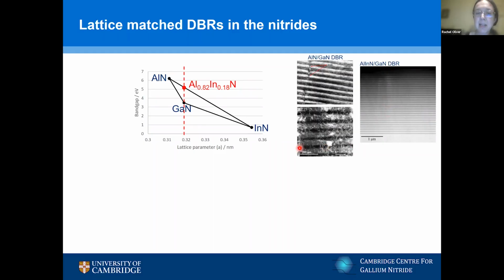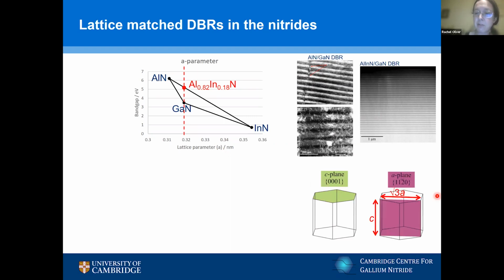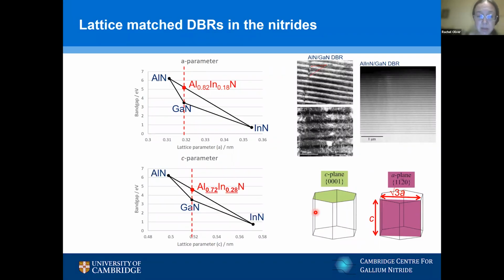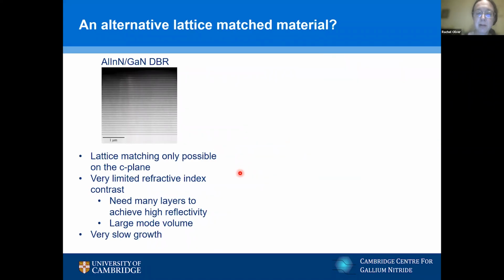And that's great. But the lattice parameter I'm looking at here is the A lattice parameter. If I'm looking at C plane, the A lattice parameter is all I have to worry about. If I'm looking at A plane, I also need to worry about essentially the height of my hexagonal prism, which I'm indicating as the C lattice parameter here. So now we need to look at the C lattice parameter, and the same thing, lattice parameter versus band gap, and you can match gallium nitride to aluminium indium nitride in terms of the lattice parameter at 28% indium, which is fine, except here I need to match both A and C. And I can't grow aluminium indium nitride which simultaneously has 18% and 28% indium. This approach of lattice matching is not an option on the A plane. There is no lattice match pair. So we had to find a different lattice match material.